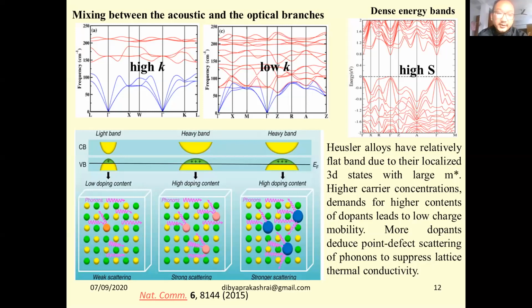Probably you will get one type of band or two types, depending upon the materials. The first one is the light band, then the heavy band. You have to find out which one is the light band and which is the heavy band, and which one is better for getting a higher Seebeck coefficient and for doping. When you dope, it will suppress your lattice thermal conductivity. The light band is not good for doping, because here the saturation point is very low. Because of that, you cannot dope a large amount of dopants. So that is the reason.